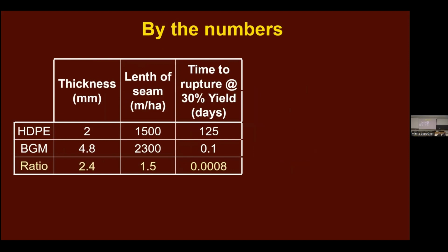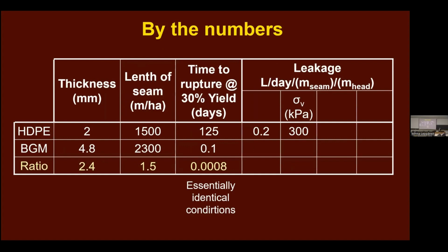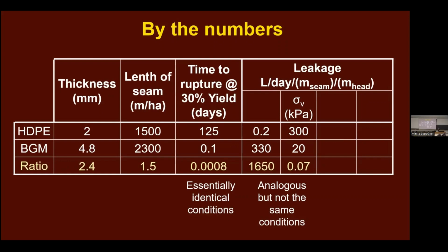And the time to rupture at 30% yield for HDPE is 125 days compared to 0.1 day. The leakage. HDPE under 300 kilopascals of load leaked 0.2 litres per day per metre of weld per metre of head. The BGM at 20 kilopascals leaked 330 litres per day per metre of seam per metre of head. A 1,600-fold difference.